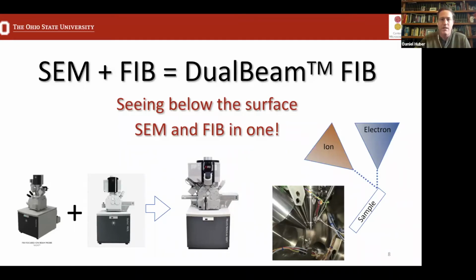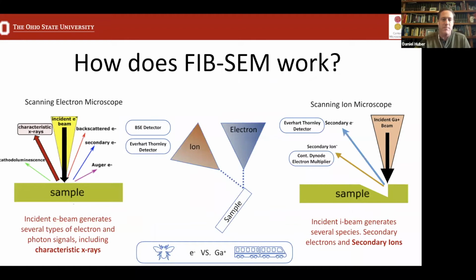That's our DualBeam FIB. So if we borrow from Steve's talk earlier on EDS, you get all the different signals that come out of the scanning electron microscopes. You got backscatter electrons, secondary electrons, X-rays, and cathodoluminescence. On the ion side, we have secondary ions and secondary electrons that come off, so we can generate an image just like we're going to be producing an image in a scanning electron microscope. You can do it with a focused ion beam.